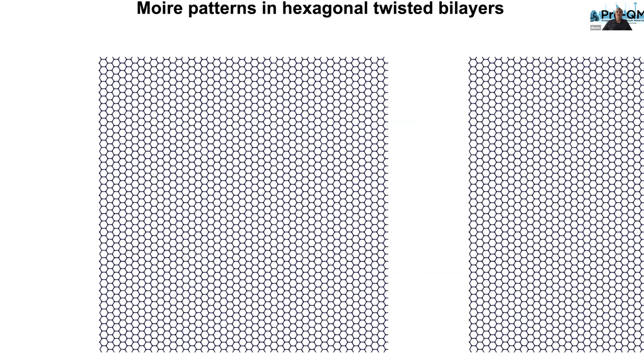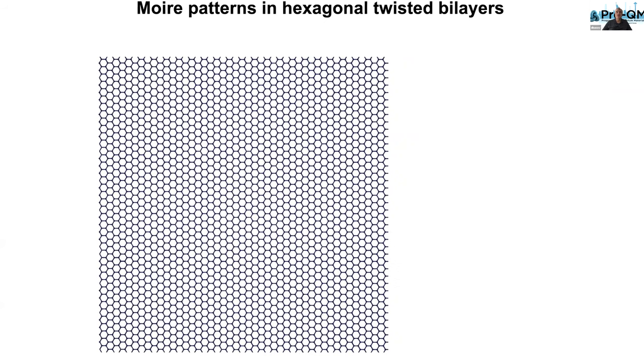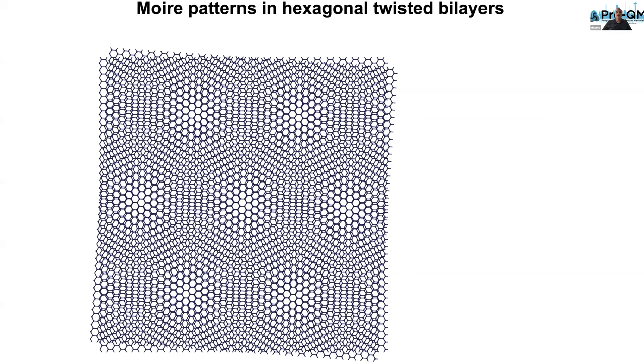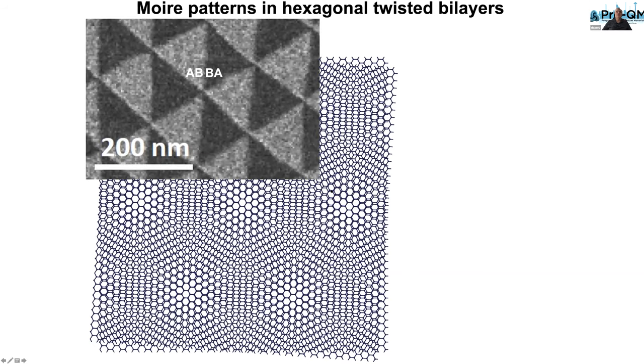Back to moiré superlattices. So you take two hexagonal sheets, you rotate one with respect to the other, and you start seeing this periodic pattern that's governed by the twist angle between the layers. If your van der Waals layers were to remain rigid, that's all you would observe. But in reality, it turns out that van der Waals layers behave as deformable membranes. And the energetics of different stacking regions that you see in this pattern is different. And because these regions can deform, they try to minimize areas where stacking energy is high, and they try to maximize areas where stacking energy is low.